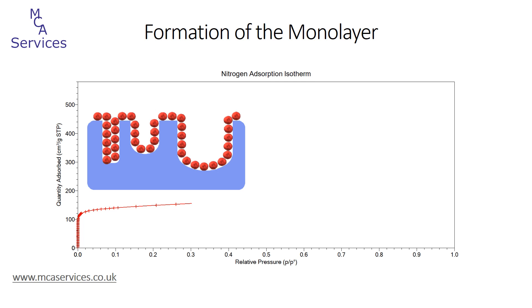Some samples, particularly microporous samples, will have the monolayer range towards the lower limit of this, or even outside of it, but we'll cover that in another video. The formation of a distinct monolayer is part of adsorption theory, but in reality it is actually doubtful whether it forms. The great majority of samples do not present the adsorbate with a homogenous surface — there will be some adsorption sites that are energetically more attractive than others. And since the enthalpy of this adsorption is low, atoms are free to desorb and re-adsorb on another site as the process continues. A process of multilayer adsorption may also start before the complete formation of the monolayer, so we're actually establishing a region of the isotherm in which statistically the volume adsorbed corresponds to just the complete monolayer.